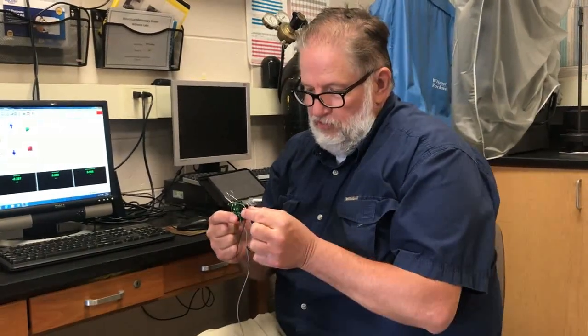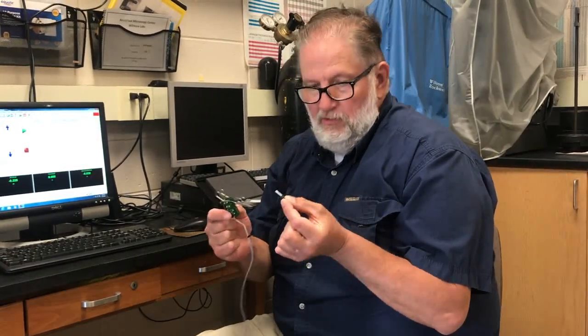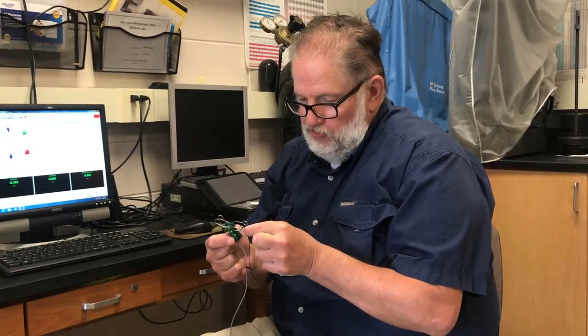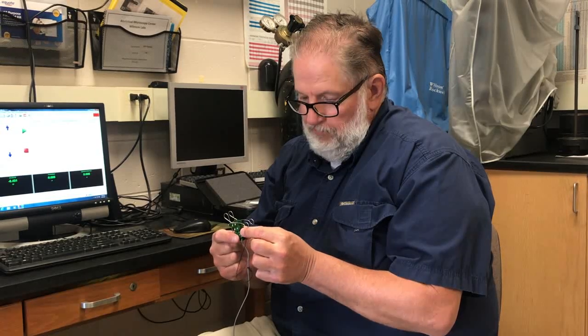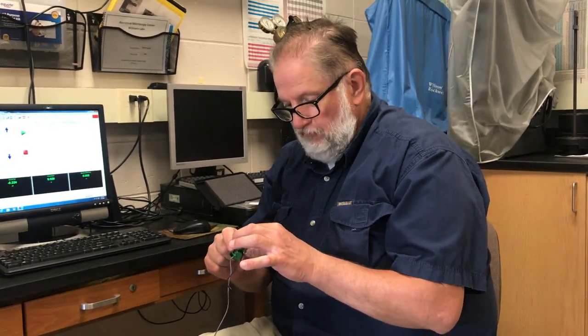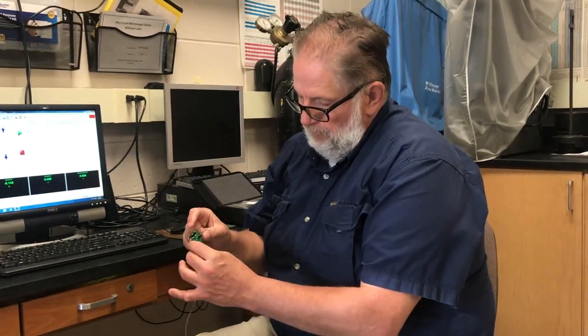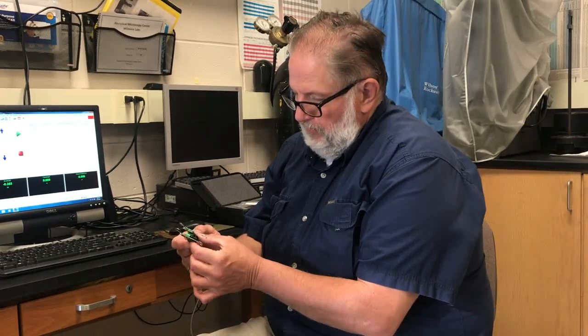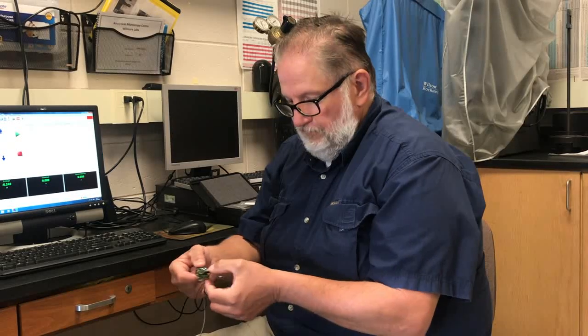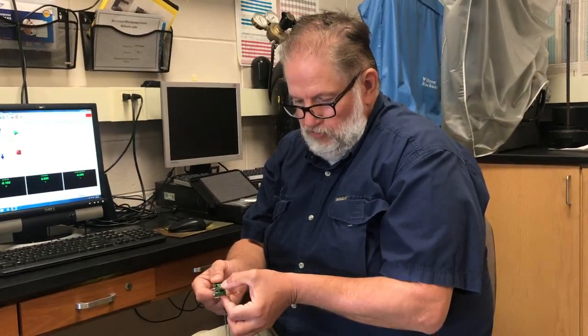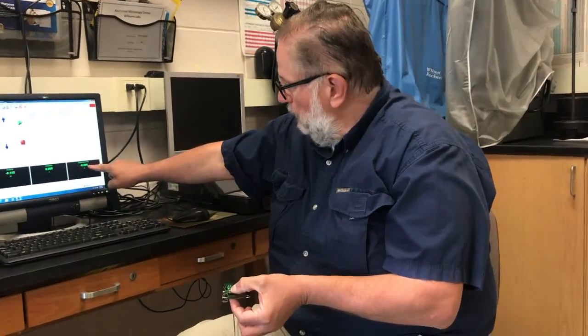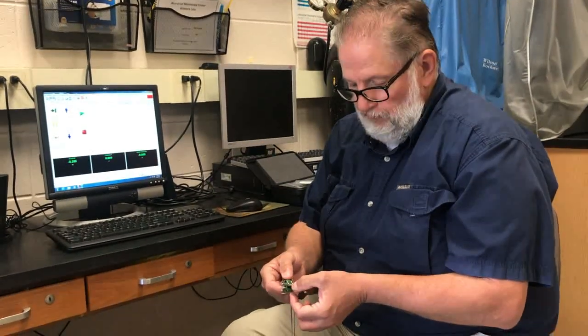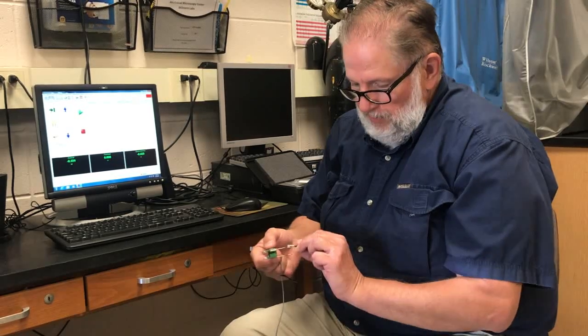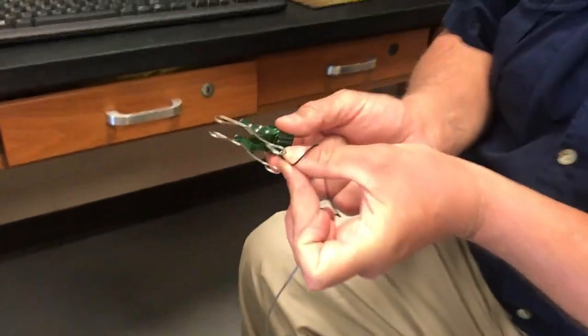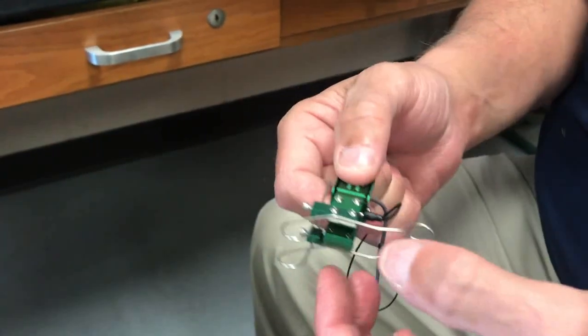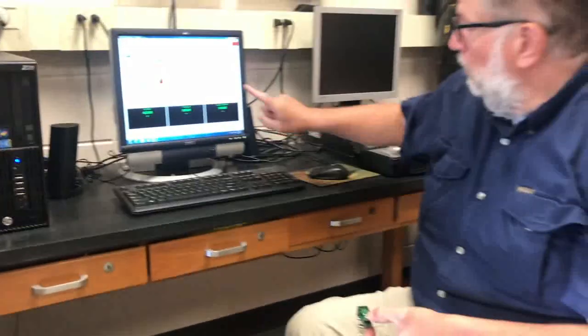It is in the resting position and can be verified because there is a little pin attached to a tether, which if inserted into the mill location for that pin between the arms of the extensometer, indicates the 0 position. In other words, if the pin is not inserted, you can squeeze the arms of the extensometer and indicate negative extension, which is only meaningful in a compression test. But if you insert the pin between the arms, right here, then you can compress the arms and it remains in the 0 position, or very close.